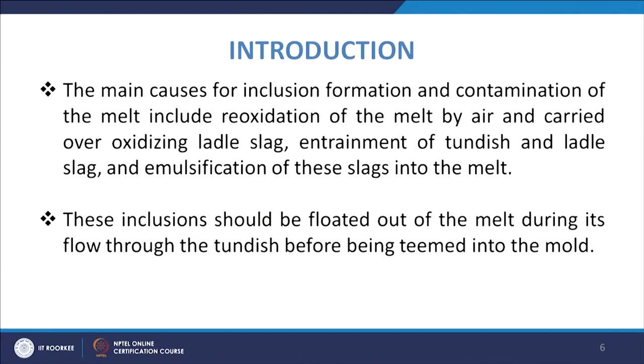The main causes for inclusion formation and contamination of the melt include reoxidation of the melt by air and carried over oxidizing ladle slag, entrainment of Tundish and ladle slag, and emulsification of these slags into the mold, into the melt. So, what we mean is that there is a large chance of contamination of the melt, and you will have to do something about these inclusions. There may be reoxidation of the melt by the air, or there may be Tundish and ladle slag entrainment.